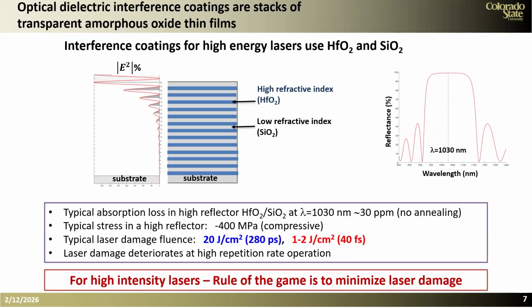So coatings are made, and I will show you how they are made, but they are essentially passive electromagnetic and photonics devices. Why do I say that? It's because a coating, like for example, a high reflector coating, like I show in here, consists of a stack of two materials that have contrasting refractive index at the laser wavelength. So for example, here I show a stack of a material that you would read as hafnium oxide, and that is the high refractive index material. The low refractive index material is silicon dioxide. Now, these materials are amorphous, and these are the type of materials that we grow in the lab. Because they are amorphous, I will call them hafnia and silica.